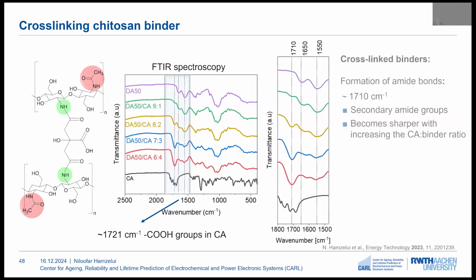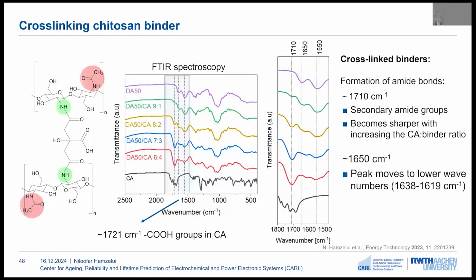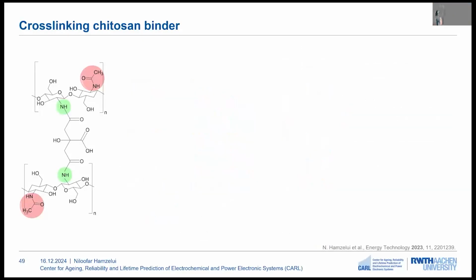And then in this region, we can see that in cross-linked binders, we can see the formation of amide bonds and the secondary amide groups. As we can see here, this peak becomes sharper with increasing the amount of cross-linker. Also at 1650, we can see that the peaks move towards lower wave numbers. Based on these FTIR measurements, we can observe that we had a successful cross-linking of the binder.